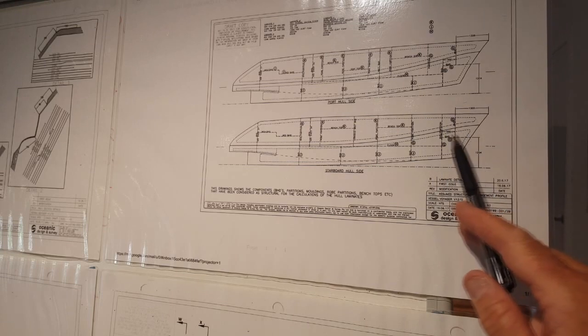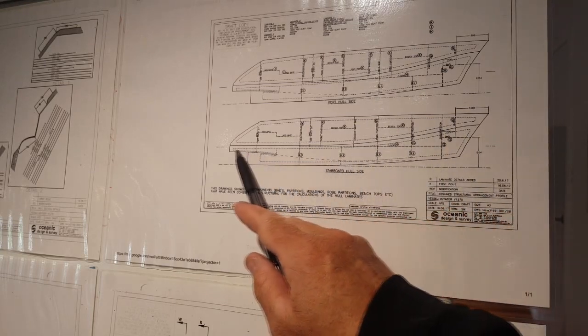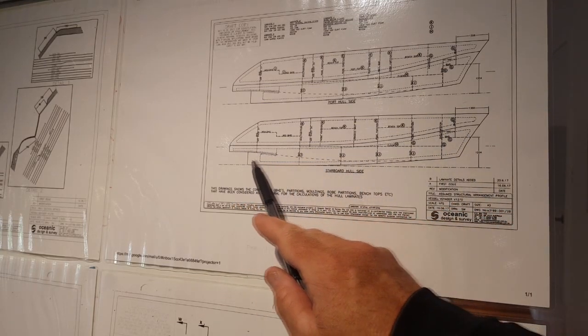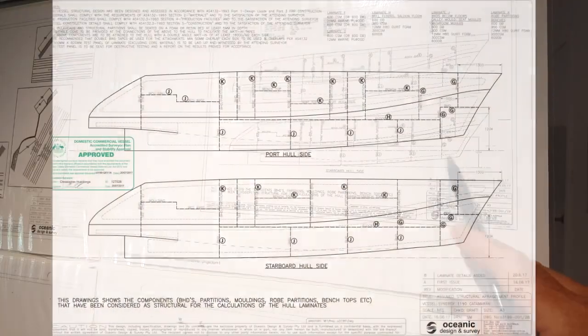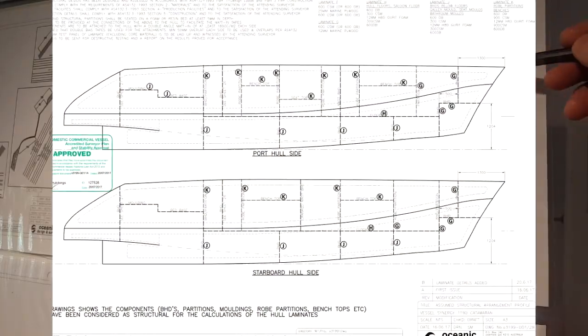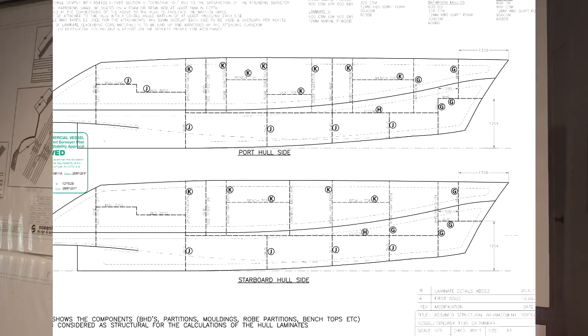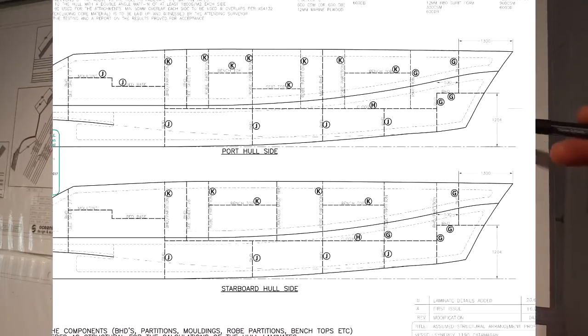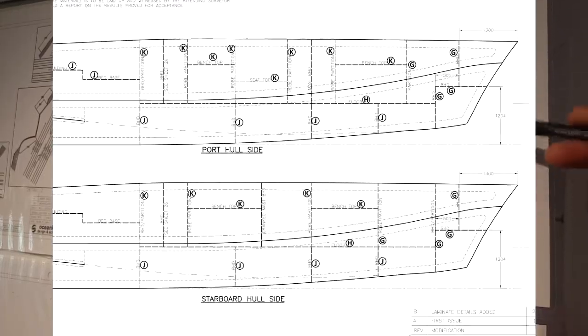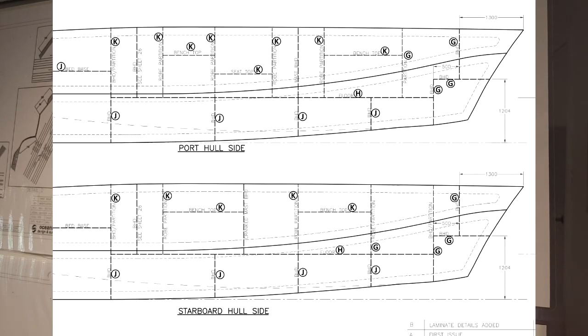Now this is actually on the outside, obviously the port hull side, and then this is obviously the starboard side. So as you can see here, we've really got quite a substantial amount of foam going down into the skeg here, and essentially running 8 centimeters from the outside or the outer perimeter of the hull, or the gunnel, and in fact the chines, allowing us to go back to solid glass at that area.